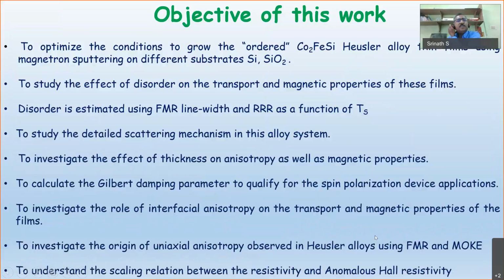So we tried to deposit these films with different degrees of order, because our idea was to see how the disorder changes the magnetic and transport properties, and how the thickness affects them. We grew these films with different disorders by varying the substrate temperature. When you are depositing the films on a substrate, we could controllably vary the substrate temperature. For a given deposition, we kept the substrate temperature constant, so that we can vary the order in this system. Then we carried out detailed transport, magnetization, magnetoresistance, ferromagnetic resonance, and magneto-optical Kerr effect measurements. We used a variety of experimental techniques to characterize and understand the magnetic properties of these systems.